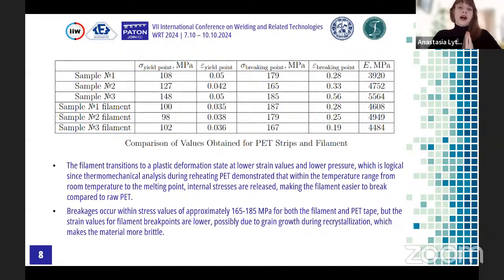So from the temperature range from room temperature to the melting point, internal stresses are released, and it makes the filament easier to break compared to raw PET, which our results demonstrate. And if we look at breaking point values, breakage occurs within stress values of approximately 165 to 185 megapascal for both the filament and PET tape. But as we can see, the strain values for filament breakpoints are lower. Possibly it's due to grain growth during recrystallization, which makes the material more brittle, but to prove it, more research needs to be conducted.